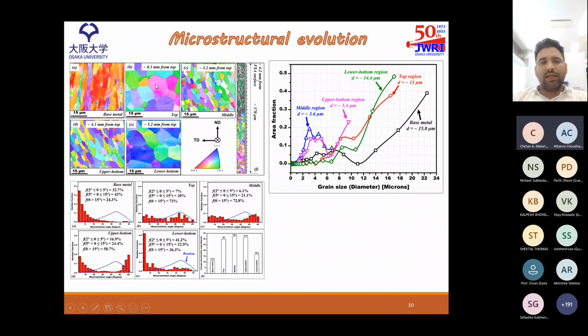Okay, so we can see that at the top, the temperature is very high, which results in grain growth, whereas in the bottom and the upper lower section, the temperature is not significantly high. So that's why, and also the IMC particles with multiple mechanisms restrict the grain growth. And so we can see that the grain size is very fine here, around 3.6 micron.